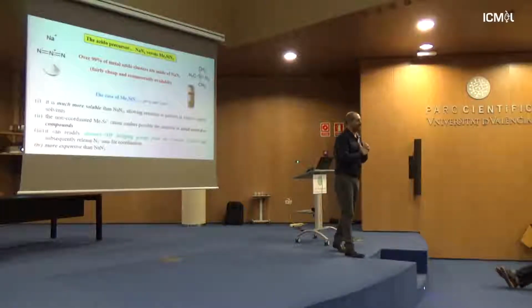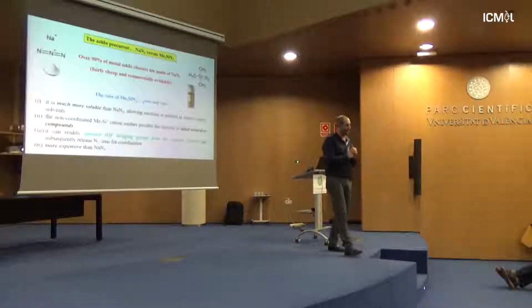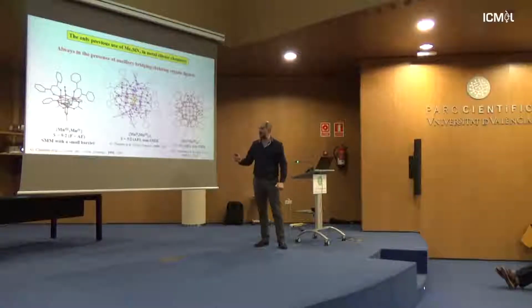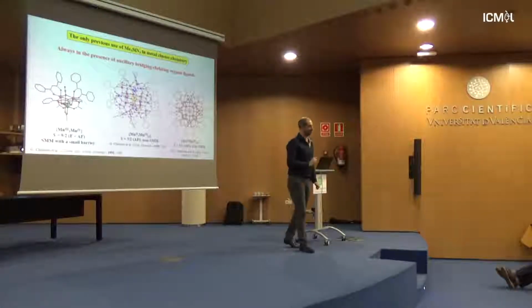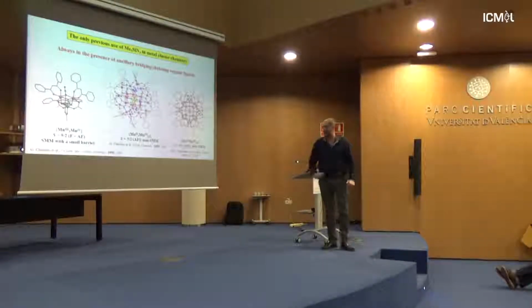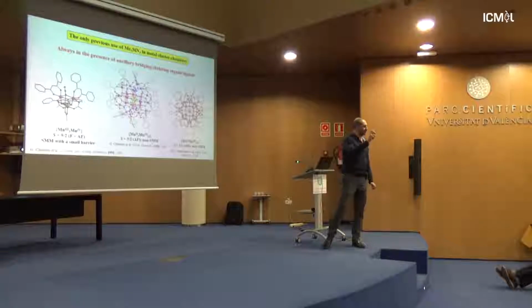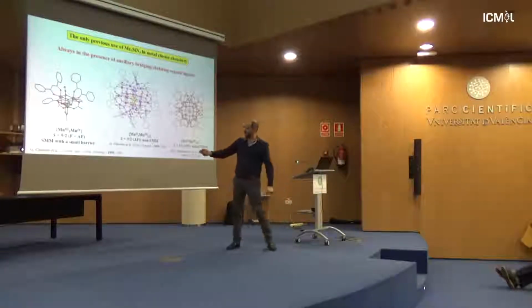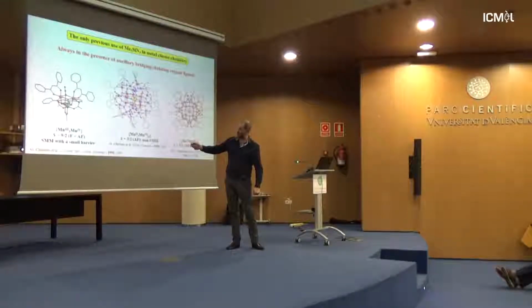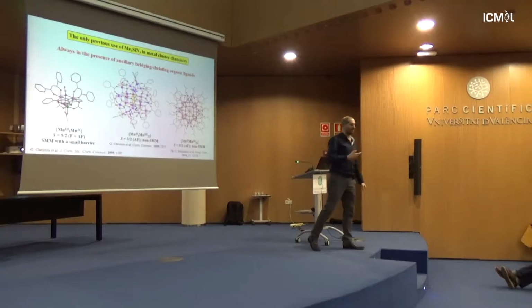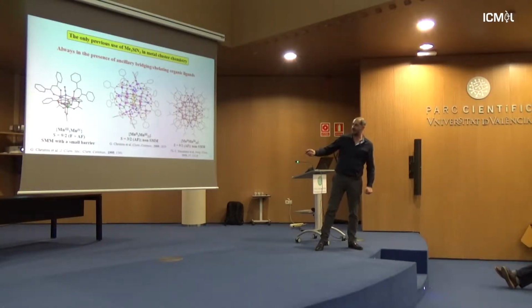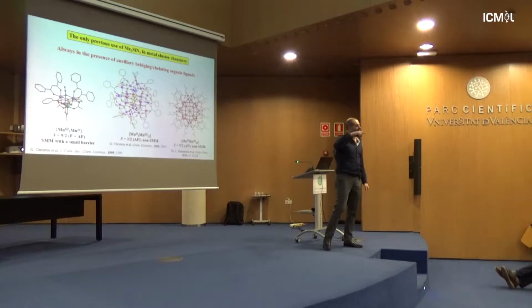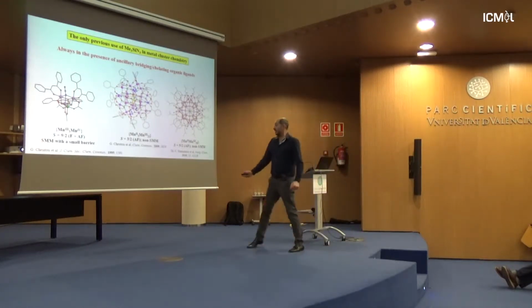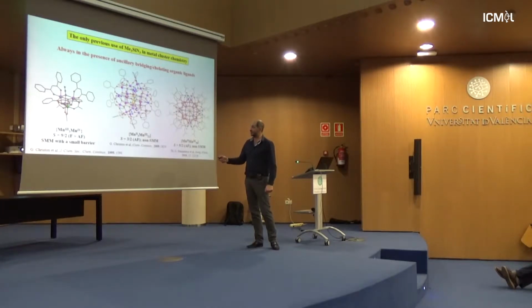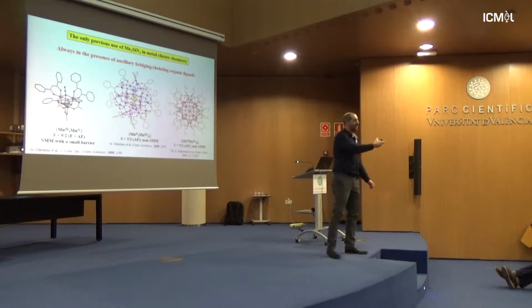But I think it was really something that we wanted to try and develop, especially given the fact that in the literature, trimethylsilyl azide in cluster chemistry was only previously used by George Christou quite a long time ago, but not for the purposes of what I'm going to show you. George Christou was trying to make those cubanes with several mu-3 bridging ligands, so he used trimethylsilyl azide in conjunction with different organic components to deliberately, selectively remove this mu-3 ligand, change it from chloride to bromide to azido and so on. A few years after, we took trimethylsilyl azide and we used it as a carboxylate remover.